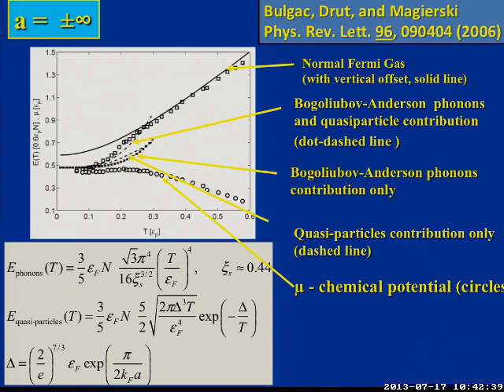And this is the chemical potential. Chemical potential is the Fermi energy at zero temperature, but then you increase the temperature and for fermions it goes negative and becomes the same thing as for bosons, so Maxwell particles. It crosses zero at about 0.7 Fermi energy. Okay. Now we're trying to understand what is this behavior here.